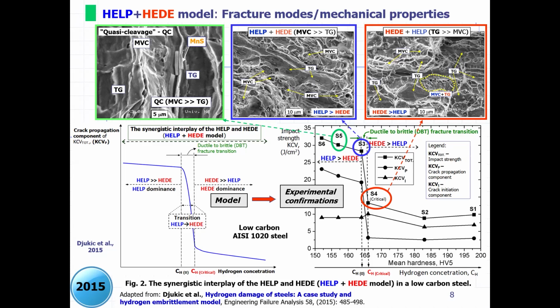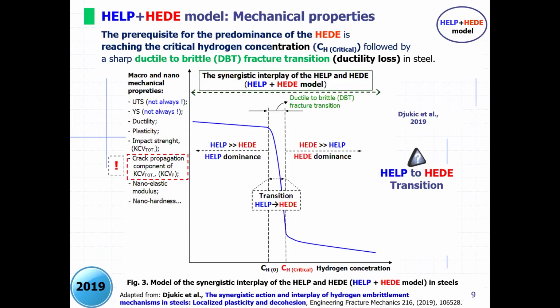And then after accumulation, we propose the local HEDE microincident concept, which tells us that when we have accumulation of large enough decohesion incidence, we still have a remaining ductility in the material, but we have a predominance of transgranular failed area, and after that intergranular, we have a very sharp drop in mechanical property, which means a drop in ductility, which finally provoked the hydrogen-assisted crack initiation and propagation, and that's the basis of the HELP HEDE model.